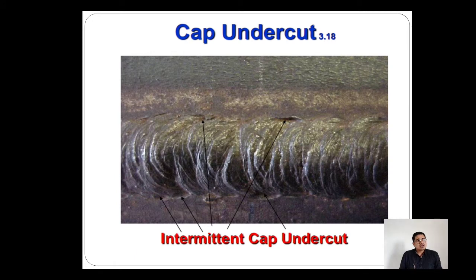So friends, the next defect we are going to discuss is the cap undercut. Cap undercut happens when the welder is performing welding, and at the time of welding the parent metal melts. So you can see beside the weld metal that some of the parent metal is melted, and it has created some notches. This is a very dangerous defect, friends, because it may create stress concentration. So normally the recommendation is, whenever a welder finds such a discontinuity or defect, he needs to smooth grind it, or if required weld it again.